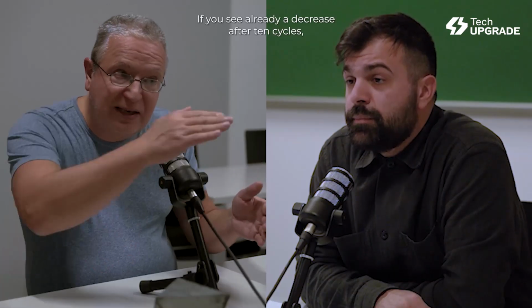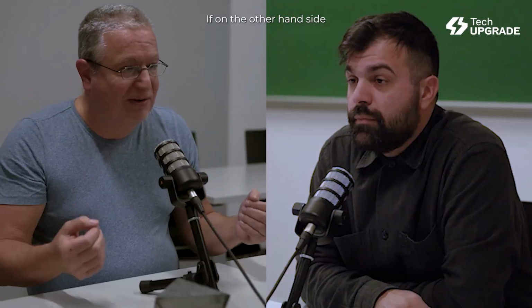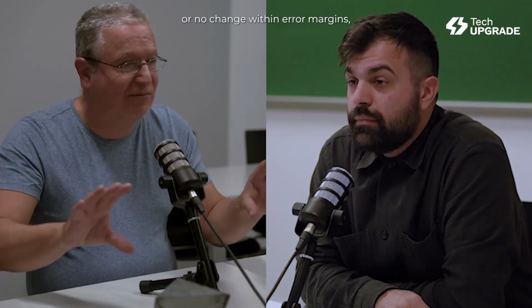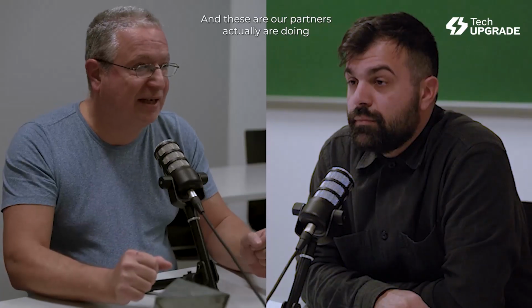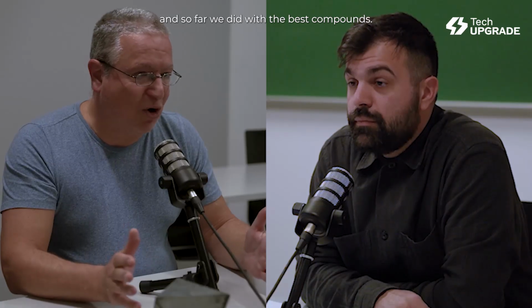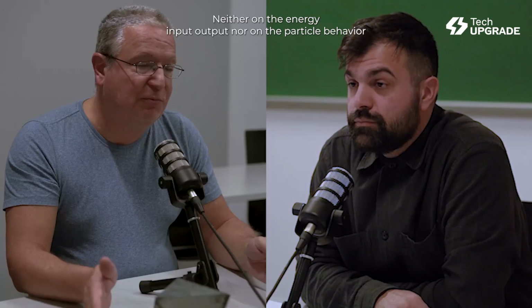If you see already a decrease after 10 cycles, there is no need to look further, because then it won't be stable. If, on the other hand, you see almost no change, or no change within error margins, I would say, in this measurement, then you run for bigger sizes. And this our partners actually are doing. And so far, we did, with the best compounds we found, several hundred cycles without seeing any deterioration, neither on the energy input output nor on the particle behavior.